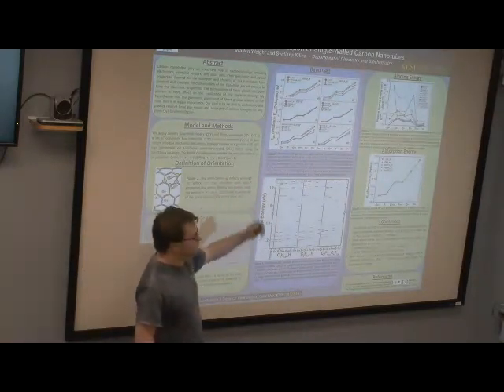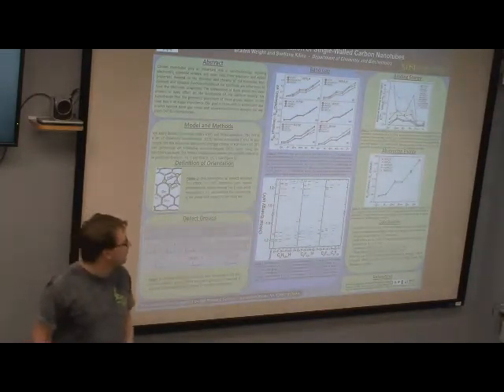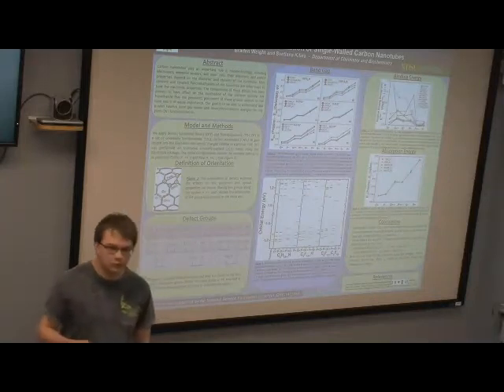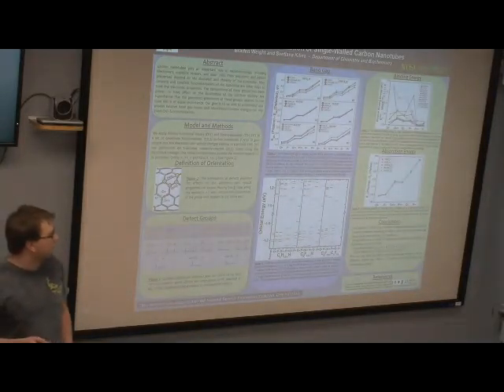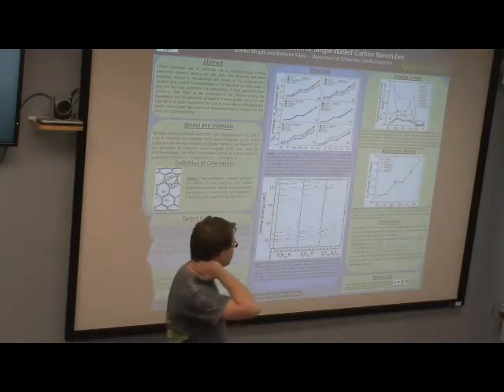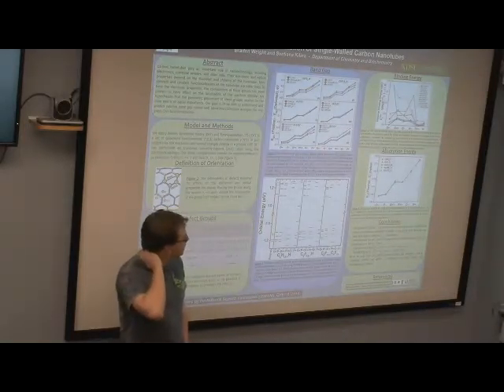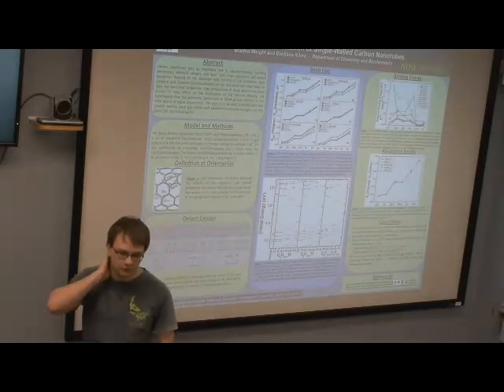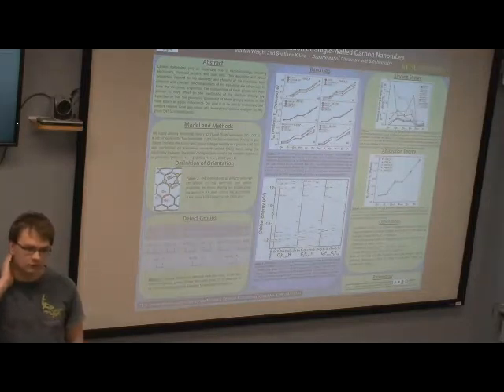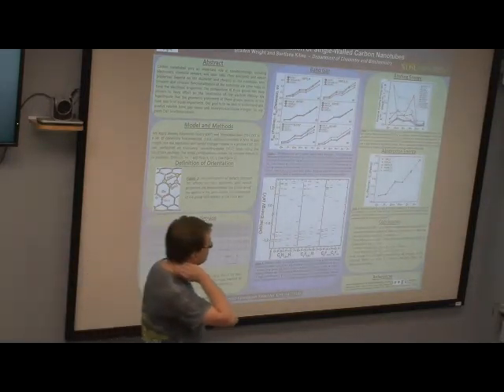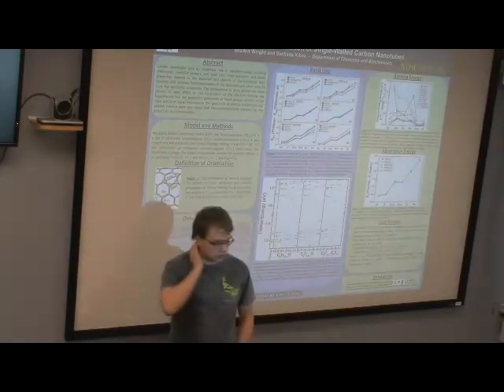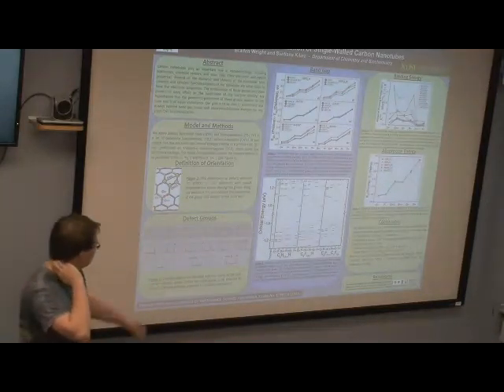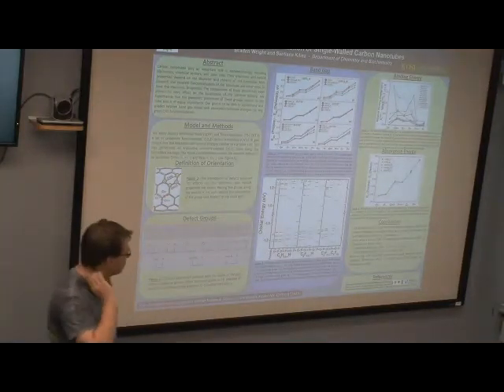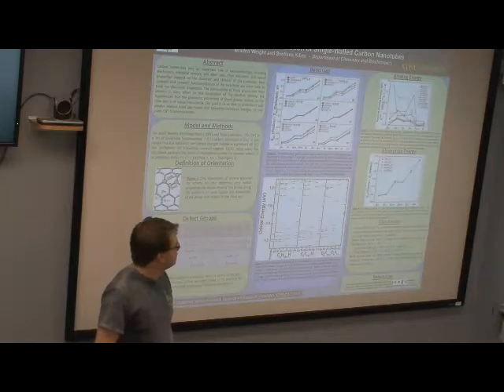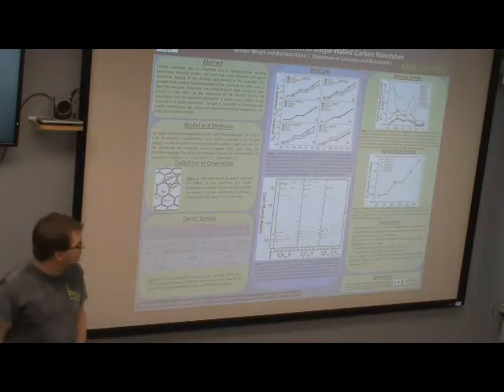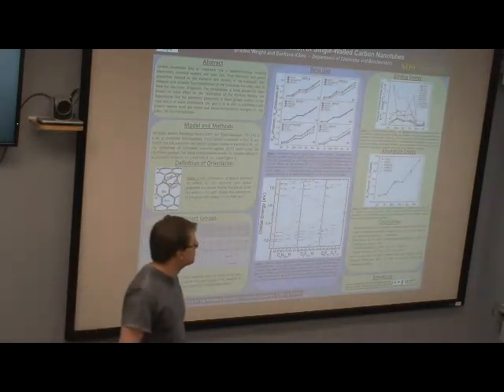Pretty trivial, it looks just like the band gap. So the absorption energy, the E11 star peak, I should say, of the absorption spectra for each of the defect orientations tracks the band gap change for the ground state geometry. And I've just shown a couple, 6 instead of the 16 or whatever that I have total, but they all follow the same trend. And so we can draw some conclusions from this.